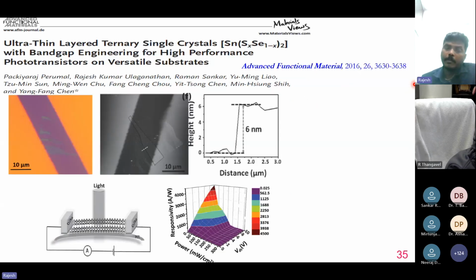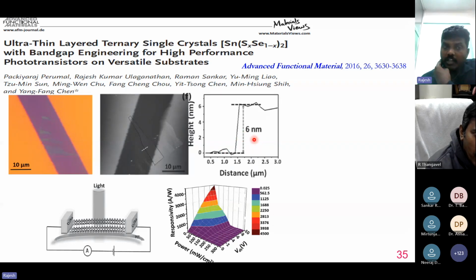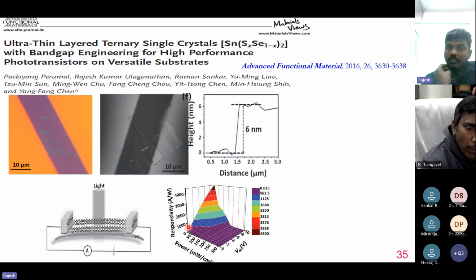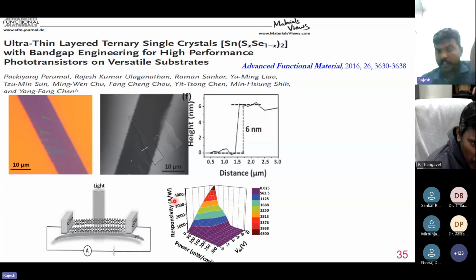Apart from the binary based materials, we are also focusing on ternary based materials in order to enhance the performance of the device, as well as to expand the broadband applicability of the photodetector. In this case, we grew a tin sulfoselenide, SnSSe, and exfoliated a very thin material, almost 6 nanometer thick, and demonstrated a photodetector device on this, and showed a very high photoresponsivity, which is quite a bit higher than the previous cases of indium selenide and germanium sulfide.